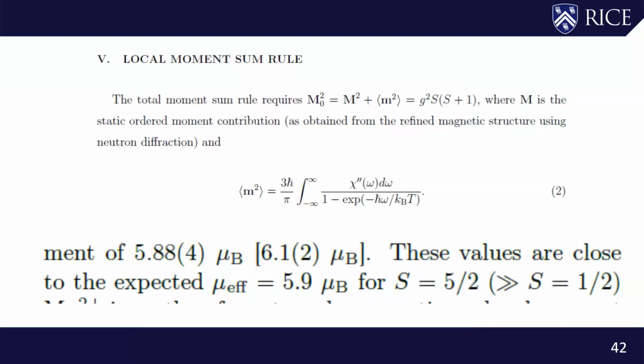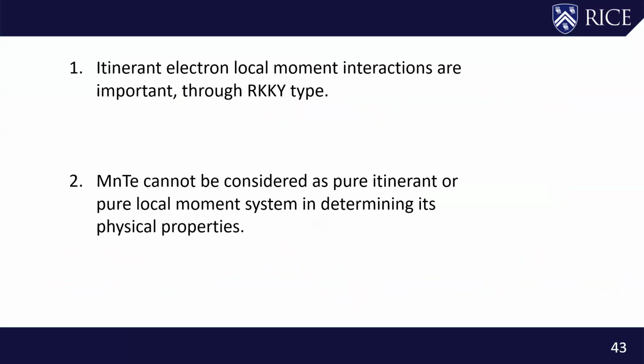Yeah. And we can do a local moment sum rule, and basically show that in both the lithium doped case and the undoped case, you can describe the whole system as basically being spin 5/2. You don't change the moment much. So really it increases the spin wave bandwidth. Yeah, so this is the conclusion that I have.